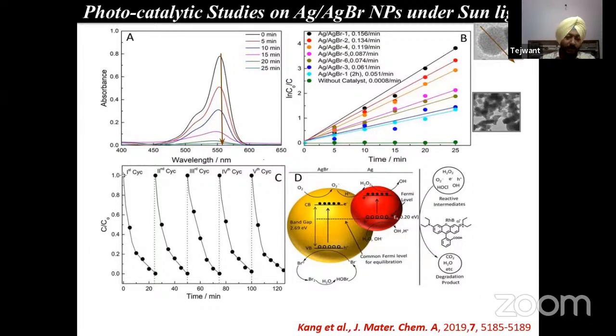Further, the photocatalytic activity has been found to be very stable for at least 5 repeated cycles of photocatalysis. And further, the probable mechanism for the photodegradation of rhodamine B dye has been proved.